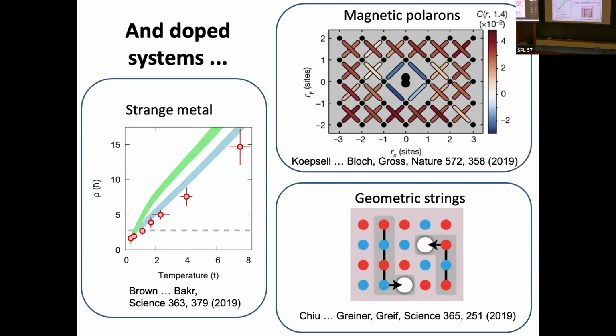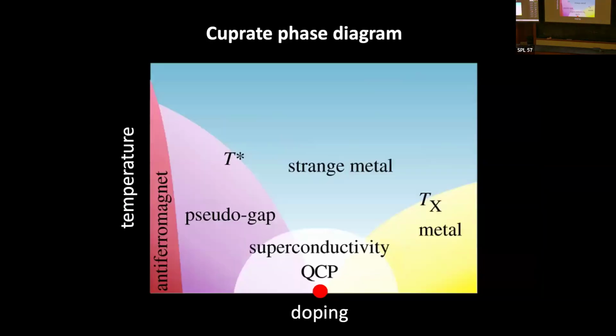Okay, so indeed, I told you that the interesting part is once you dope. So here are some key results from these doped square lattice Hubbard systems. This is work from my group where we tried to go to this part of the phase diagram here, the strange metal. So in the cuprates, what's observed is that there is a regime in the normal phase where there is a linear resistivity in temperature. If you vary the temperature of the system and map out the resistivity, it scales linearly.